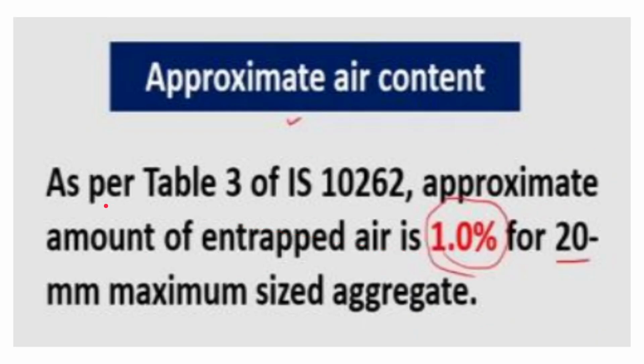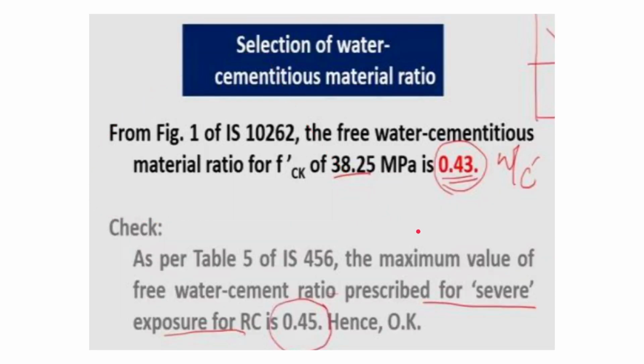Okay, so we have found the target mean strength for design. Now let us find out the approximate air content. As per table 3 of IS 10262, the approximate amount of entrapped air is 1% for 20 mm nominal maximum size of aggregate, as we have seen. They have considered 20 mm NMSA, so for that 1.0% is prescribed for entrapped air as per table 3 of IS 10262. Then, as we know, we have to find the water cement ratio